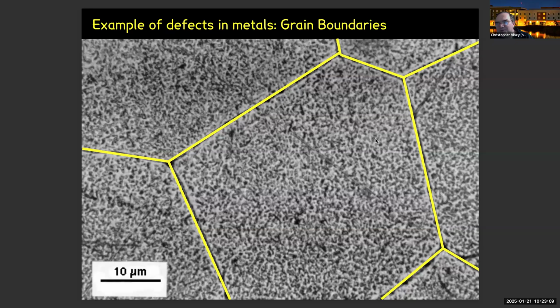Except if you do this at a high temperature, think of those boundaries as where the crystals really don't join up that well. So it's fairly easy to melt, really. Metals always melt from the grain boundaries inwards. The grain boundaries melt first, and then the middle of the grain. So you go to high temperatures, and you can slide the grains past each other. And so at high temperatures, big grains are actually better than small grains. At low temperatures, small grains are better than big grains, if you want to strengthen the material.